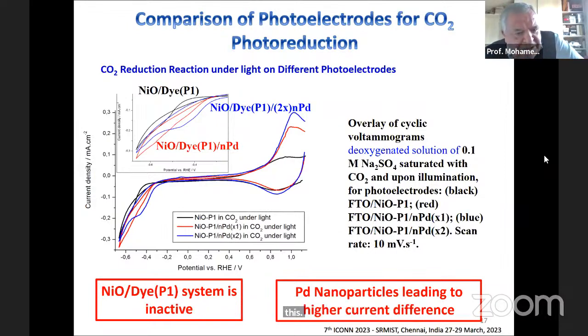So this is another, larger potential range for the three electrodes: nickel oxide modified by the dye, nickel oxide modified by the dye with one amount of nanoparticle, and twice the amount of nanoparticle of palladium. And then you can see here the effect can also be seen, but the most important is here. As you can see, when you have the nickel oxide with the dye, there is not really a great effect.